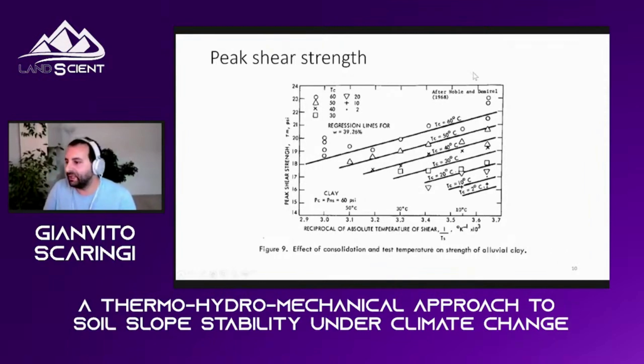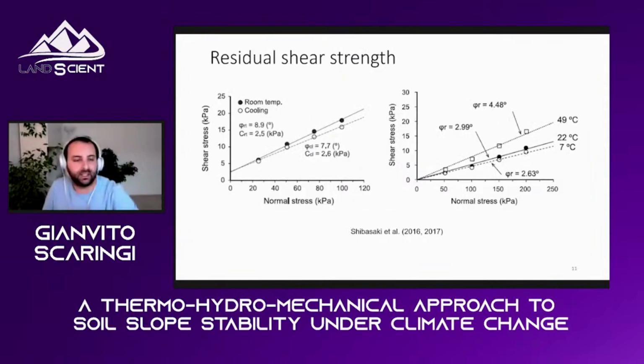But in general, if you look at the picture, on the horizontal axis, you have the reciprocal of the absolute temperature. Here you can get the actual temperature, on the right, low temperature, on the left, high temperature. And these lines, they are sloping towards the left, meaning that at a given temperature of consolidation, the peak strength decreases with increasing temperature of shearing. So if you have a consolidation at a certain temperature, no matter what, if shearing or if failure occurs at higher temperature, the peak will be lower. So actually failure should be easier. Very interesting result, but let's move on from the peak to the post-peak to the residual shear strength.